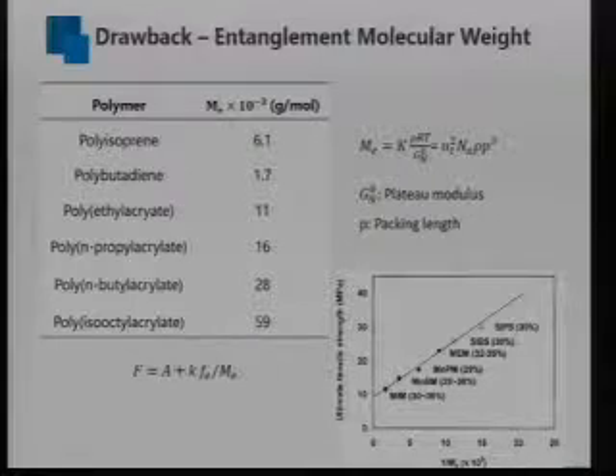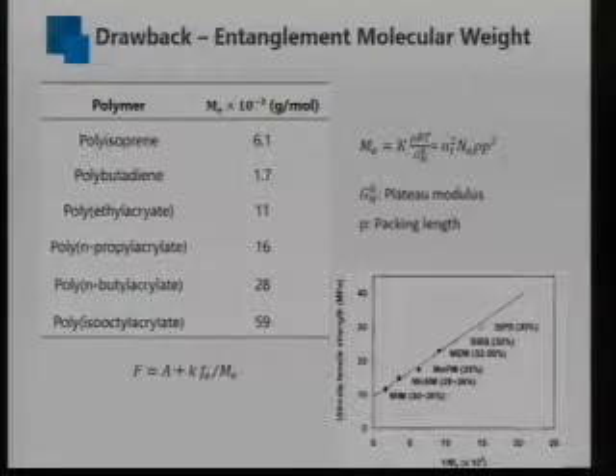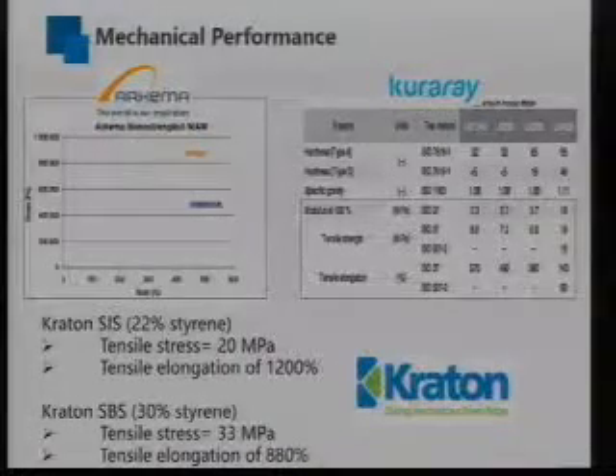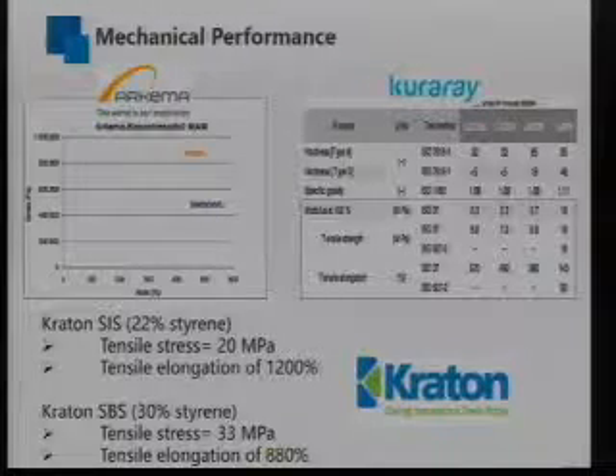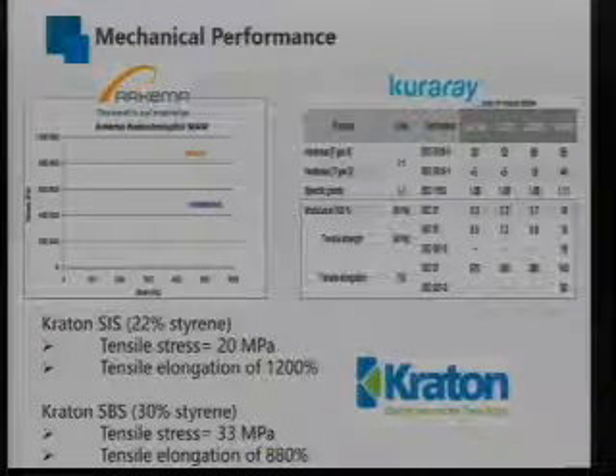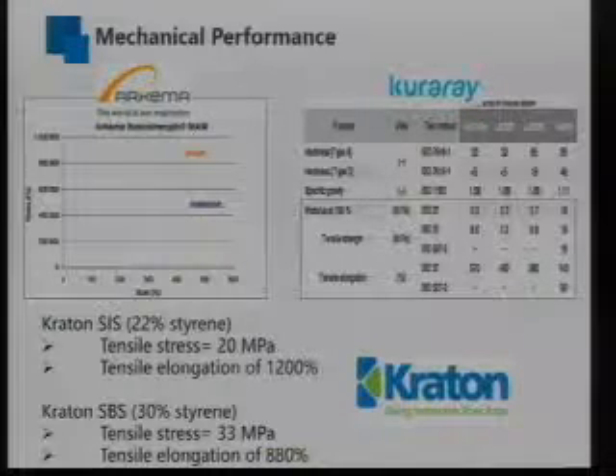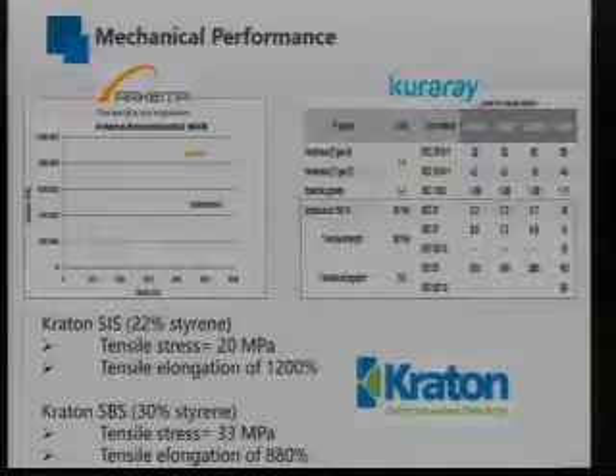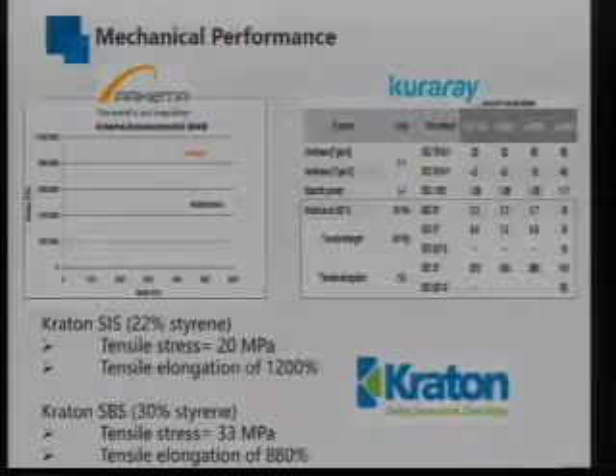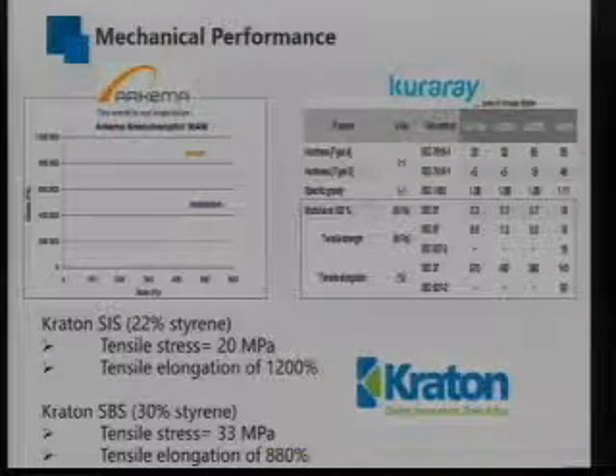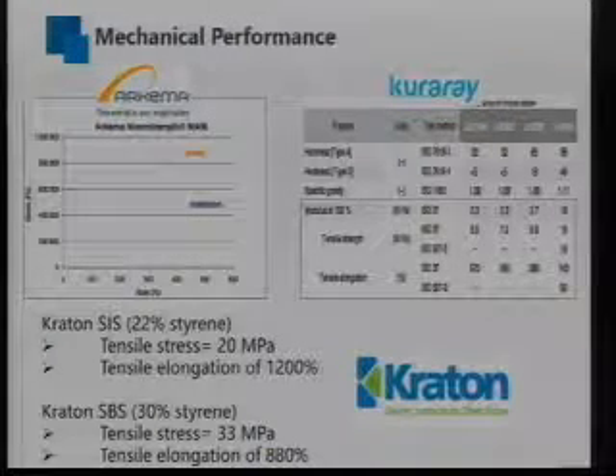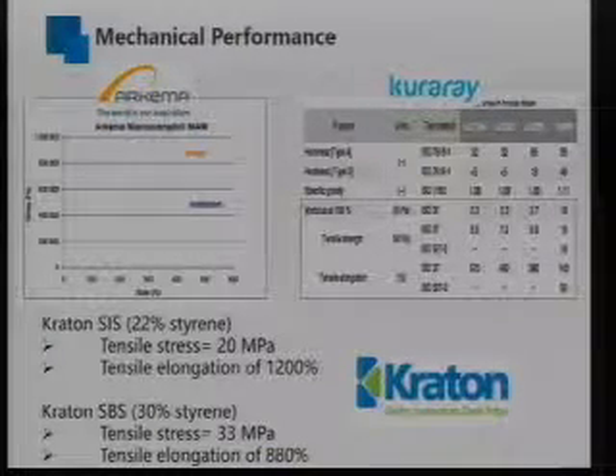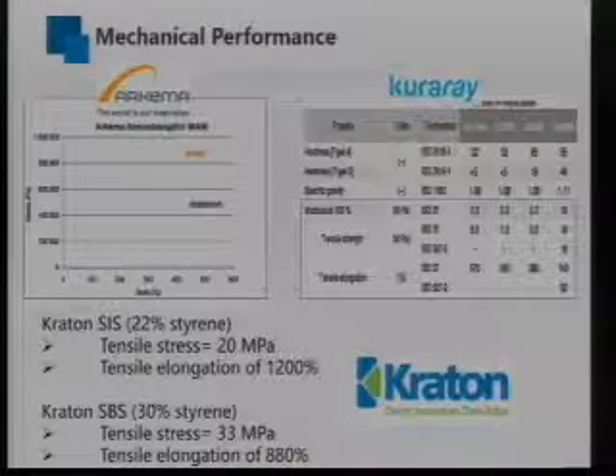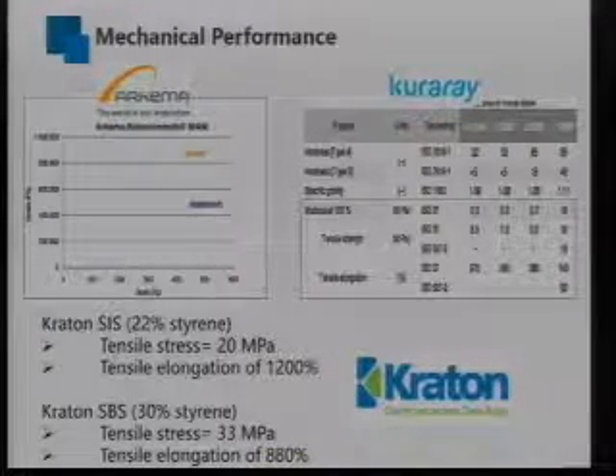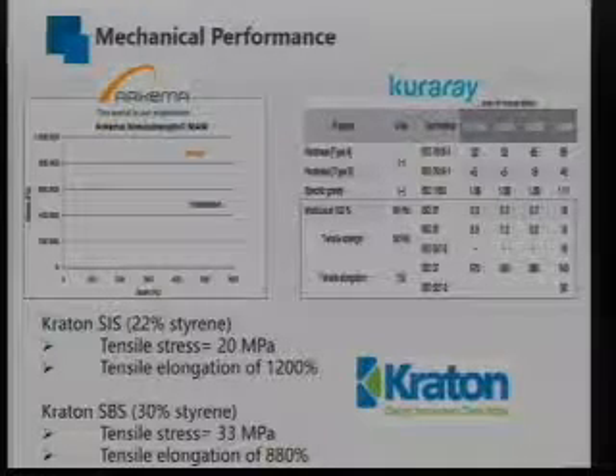So our work is focusing on how to improve the mechanical property of acrylate-based thermoplastic elastomers. And here are several examples of acrylate-based thermoplastic elastomers. For Kurarity nano strings, they always have an elongation lower than 500%, and the mechanical strength is always lower than 1 megapascal. For another kind of acrylate-based thermoplastic elastomer, Kraton successfully reached a mechanical strength as high as around 20 megapascal. But for this product, its elongation is only 140%.